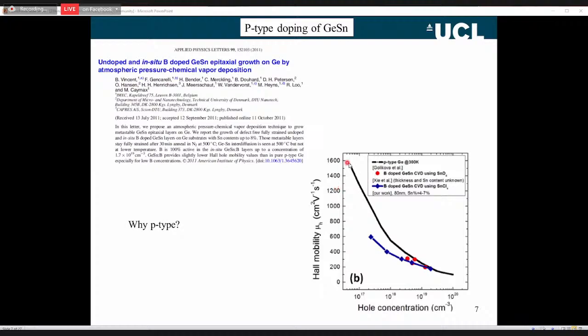You can see here, this is the hole concentration caused by doping. So actually boron into the material. Boron acts as a dopant. It also introduces scattering, so the mobility drops. If you were to do a Hall measurement of room temperature mobility, this is germanium, the solid black germanium. You can see the mobilities are actually quite high. For room temperature, mobility is quite high. What happens when you put boron into germanium-tin is the mobility drops, but it's not too bad.